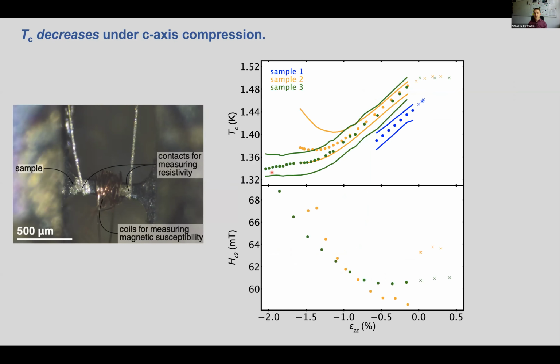And now my final slide, I show you Tc as a function of c-axis compression. My student Fabian Jerzembeck was able to compress the sample by 2% elastically. And then what we see is that Tc decreases. And that's a mystery. If we have an even parity order parameter, why should Tc decrease as we are increasing the density of states? For proof that we are increasing the density of states, you can look at the upper critical field, and that is increasing as we apply this c-axis compression.